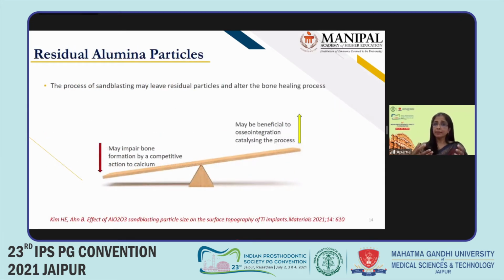Now, I mentioned earlier that it's quite natural for you to find some embedded sandblasting residual particles on the surface of the implant. The fact that the sandblasting leaves residual particles may or might not be beneficial. There are two schools of thought here. Some researchers feel that the residue may impair bone formation by a competitive action to calcium, while some others feel that the residue may benefit the osseointegration. It can actually help in catalyzing the process. But nobody really knows for sure. But most of the researchers believe that the presence of these residual particles may impair the bone formation. So this is considered as one of the most important drawbacks as far as sandblasted implants are concerned.